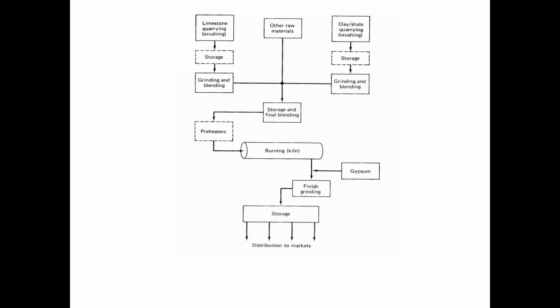So the production process, just a schematic overview of that, is shown there on your screen. We start with our raw materials there at the top of the slide, our limestone, our clay and shale, and our other raw materials that contribute to the oxide content of our cement. So we grind those materials down and we proportion those based on the particular design that is being used for the Portland cement. Grind those materials down and we blend them in proportion. And then we run that blended material through a kiln. Heat up that material such that it combines chemically with each other.